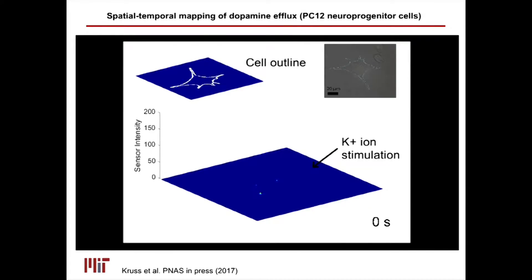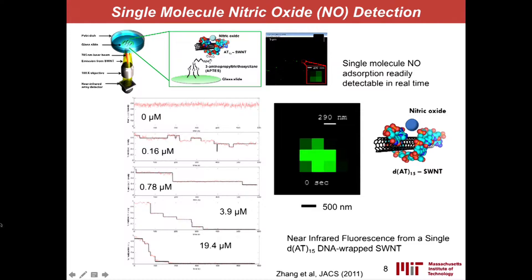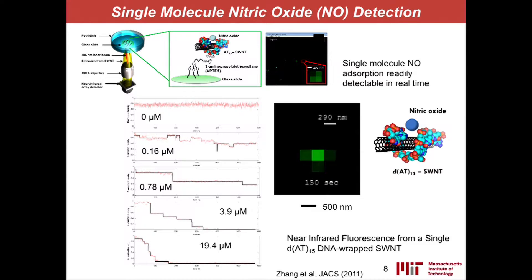You can detect down to single molecules with many nanosensor transducers — a fluorescent carbon nanotube is one. We've done a lot of work detecting nitric oxide. Here you're seeing single nitric oxide molecules binding from the bulk at room temperature in the environment. You can make a nanosensor transducer that can count individual molecules. We've solved the detection limit problem — there's no concentration below which the sensor doesn't work. The question is making it selective, and we've made a nitric oxide sensor.